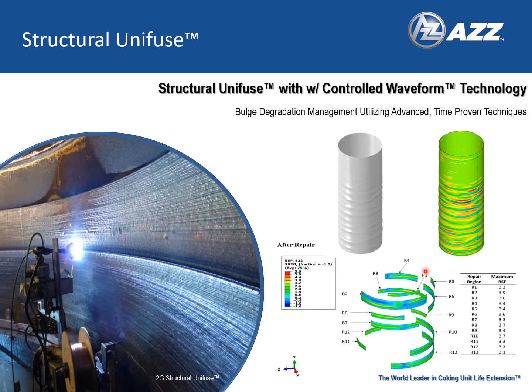For these areas, a structural overlay is designed and iteratively reanalyzed using the same model. This results in an overlay design that mitigates the continued growth of the bulging and the eventual cracking that can result. Critical to success of this application is the application of a high-quality, homogeneous deposit with excellent geometric profile. The control waveform technology included in AZZ's proprietary tooling provides a high-quality deposit that exceeds the rigorous requirements for a successful repair.